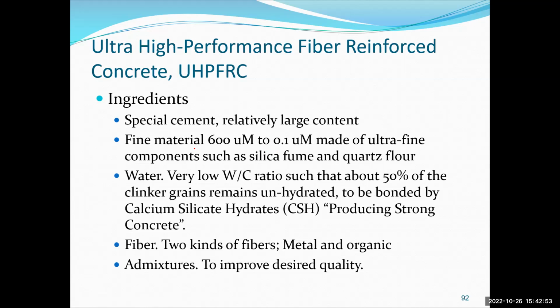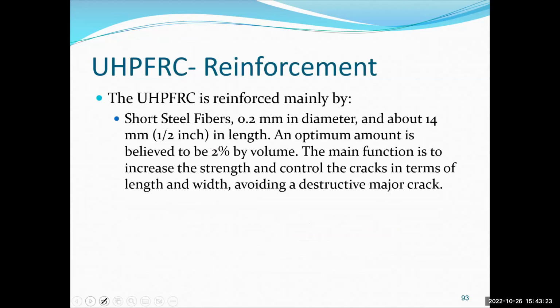And we use even finer materials, approximately 600 micrometer to 0.1 micrometer. We use water cement ratio 0.11, very small. That means there's no excess water for sure. And sometimes you use metal fiber to increase the strength here again, and organic fiber to protect the concrete if the concrete is subject to fire. Now, admixtures, we can use admixture later on. So that's the whole secret.